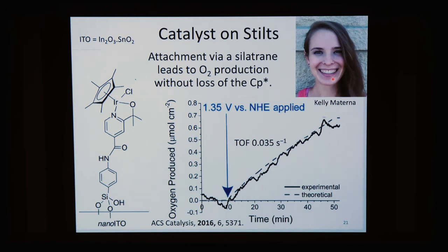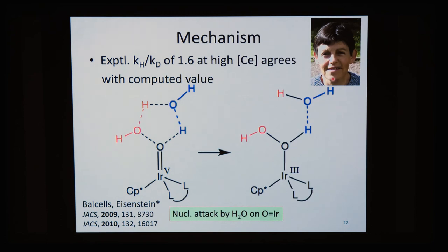So this was an indication that putting things on electrodes doesn't necessarily give you the same thing as you had in the solution phase. Now here's Odile helping us out once again. An experimental hydrogen deuterium isotope effect of 1.6 agreed with the computed value for her mechanism. So her mechanism involves attack of the red water on the oxygen attached to the iridium.